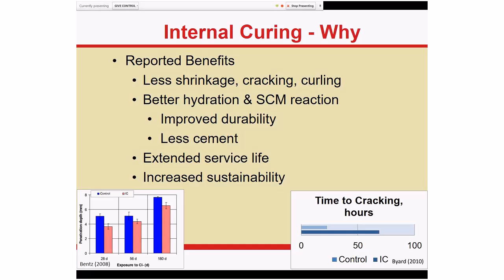In the literature, there's been a lot of work carried out on this over the last few years. Jason Weiss has done a lot of work. Dale Bentz from NIST has also reported a lot of benefits. I'm not going to go into too much detail, but in general, it's less shrinkage, which we want, reduced cracking, which we want, reduced curling, which we want, better hydration, better reaction of supplementary cementing materials, which is also a good thing because it means that we could actually insert more supplementaries into the system and again buy better performance at the end of the day.